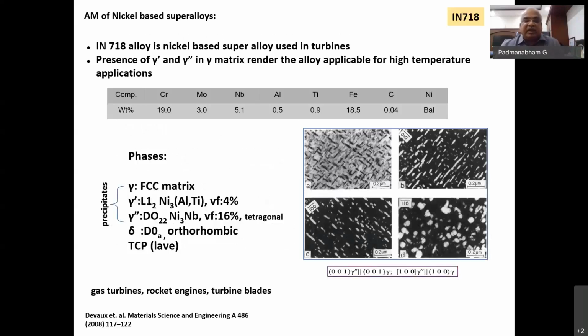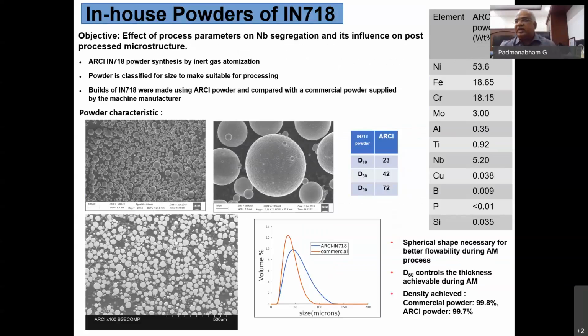The next alloy, the most popular alloy, is the nickel-based superalloy used in blades of gas turbines, rocket engines, turbine blades. This is also a complex material. We have strengthening phases like the gamma prime or the gamma double prime in a gamma matrix and the undesirable phase like the Laves phase. So the whole solidification behavior and the heat treatment behavior has to be optimized to minimize the Laves and maximize your gamma double prime or gamma prime phase in the material. And we did extensive work.